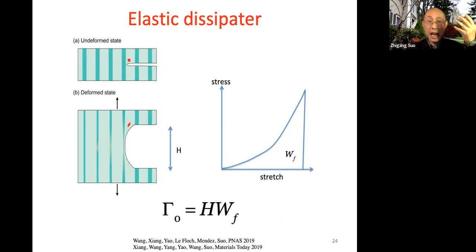Now, this is an elastic dissipator because both matrix and the fiber are elastic. There's no other dissipation mechanism. Before this fiber breaks, everything is elastic, it doesn't suffer fatigue. And when it breaks, it dissipates energy over the entire length of the fiber. So if this is your stress-strain curve, the work of fracture underneath the curve is WF, but your toughness is the macroscopic length H times this WF. This is an enormous number.